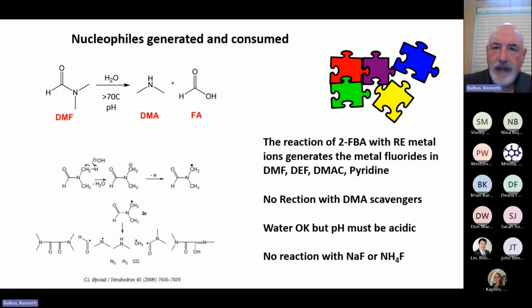So one of the things that we discovered was that this was very solvent dependent. So you could have water around, but you needed a solvent like DMF. So DMF, DEF, DMAC, pyridine, all these solvents here seem to work. And one of the problems with something like DMF is I call it a very dirty solvent. In other words, it breaks down very easily, and you'll have a mixture of not only DMF, but also dimethylamine, and you can end up with formic acid in your solution as well. And there's even been reports that you can end up with free radicals in your solution as well.